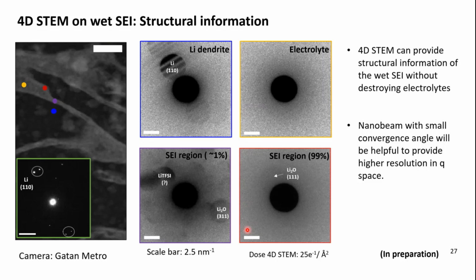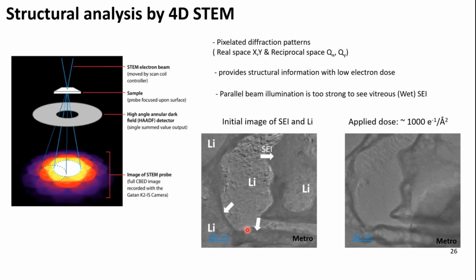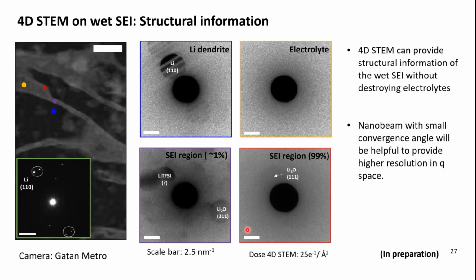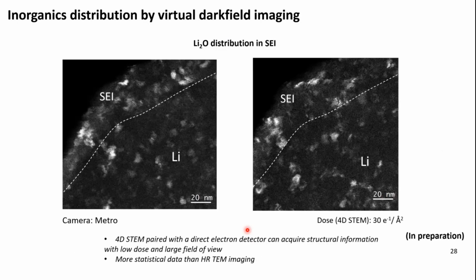I'm guessing that for the dark field image that you showed, you did that in Digital Micrograph, right? Yeah, I use Digital Micrograph to make the virtual dark field image here. I use the software to put a virtual dark field aperture so that it can readily show where lithium oxide or other particles are distributed in the SEI. Because this is really a basic first analysis that's really easy to do in our software. But there are sort of infinite possibilities in the 4D data cube. I look forward to seeing how you can analyze all that data.